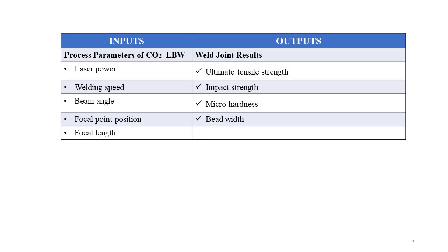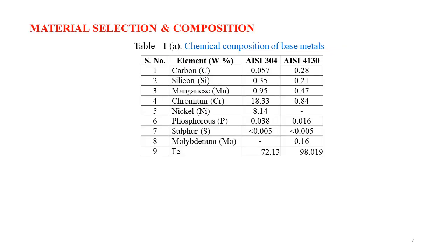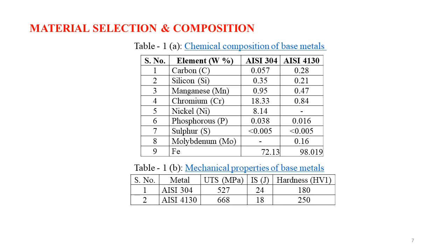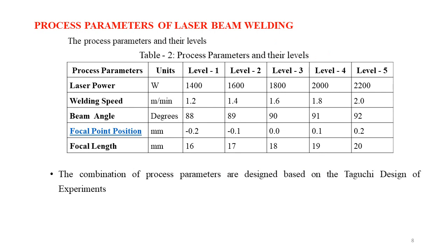The input process parameters are laser power, welding speed, beam angle, focal point position, and focal length. The weld joint responses are ultimate tensile strength, impact strength, micro hardness, and bead width. Next, the investigation materials, compositions and mechanical properties. In the laser welding process, five process parameters with five levels are considered.